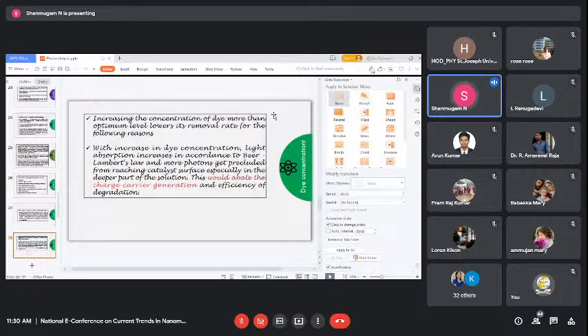Then increasing the concentration of the dye more than the optimum level lowers its removal rate for the following reasons. If you increase the concentration of the dye, the catalytic activity may not be increased, it may be suppressed. With the increase in dye concentration, light absorption increases in accordance with Beer-Lambert's law, that is, absorbance equals epsilon times path length times concentration of the solution, so that more photons are precluded from reaching the catalyst. They are not allowed to reach the catalyst, especially the catalyst available in the interior.